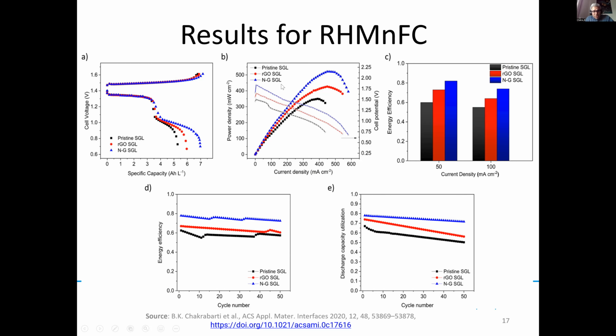One thing to note is that standard flow batteries use carbon felts, or thick electrodes, to have good electrochemical performance. In our case, we're using much thinner carbon papers, which are less porous. But if we modify them with the nitrogen doped graphene, we get almost the same power density as with a standard felt used in a manganese flow battery. So we are getting similar performance to a standard flow battery using a carbon felt.